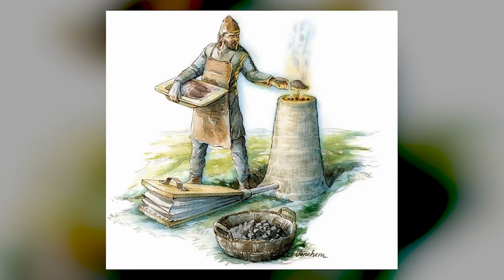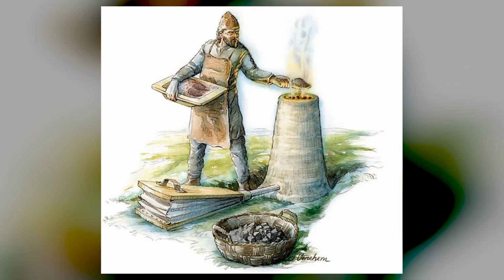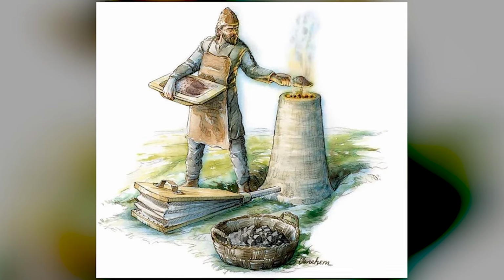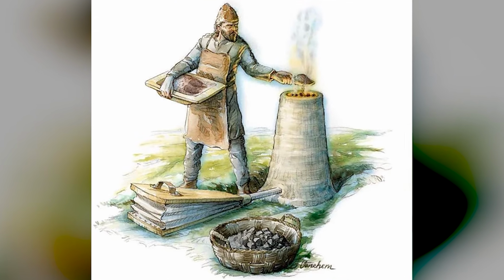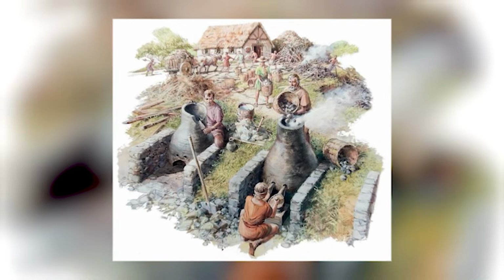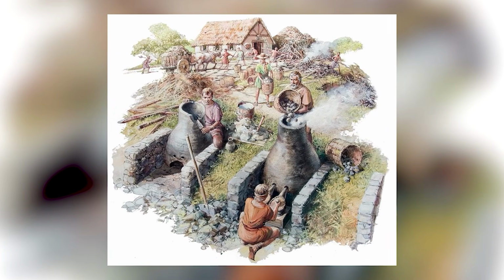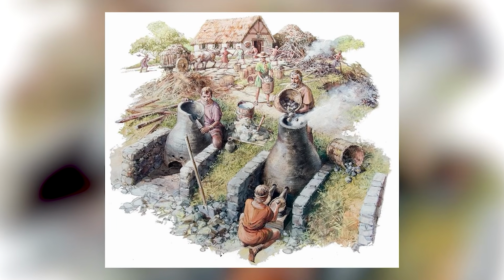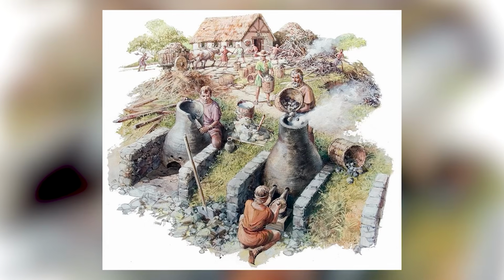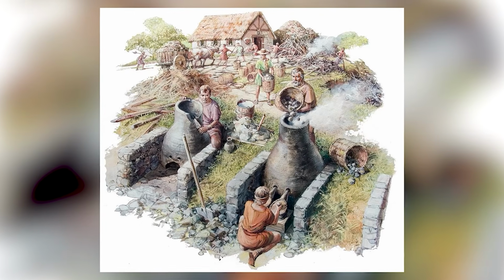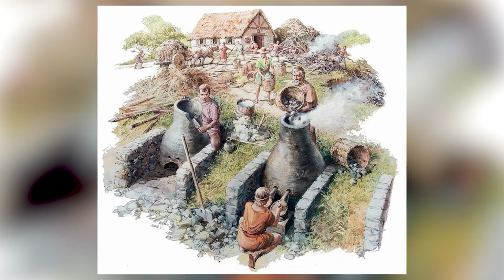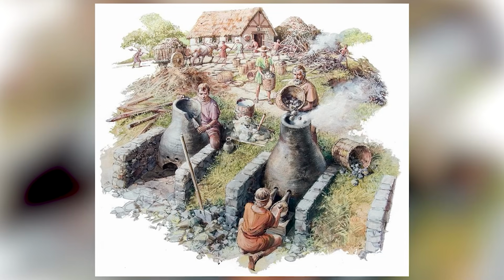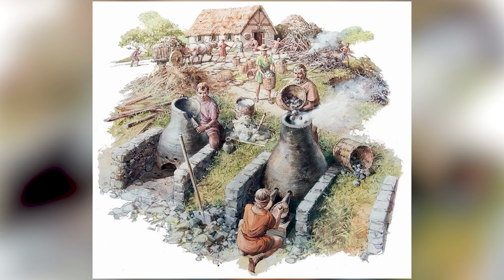But all the rocky impurities in the ore, the silica and other minerals, those did melt. They formed a glassy slag that dripped down through the furnace. The solid iron particles sank into this molten slag bath, clumping together at the bottom into a spongy mass called a bloom. After hours of work, the smith would crack open the furnace and pull out this incandescent blob. It looked more like volcanic rock than metal.